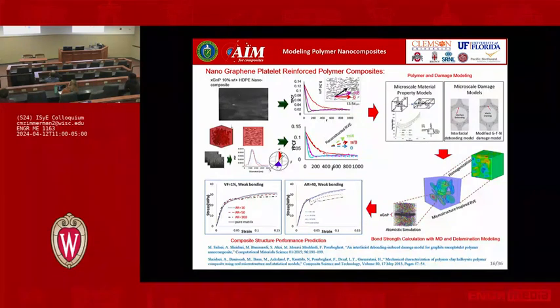So we looked at two-point correlation functions to get information about the volume fraction, and what the distribution of that would be as a function of size as it becomes bigger with respect to these arrows put in here. As an example, this part is shown here in black and white, so you can see only the fibers, and you can see that they have a particular orientation.